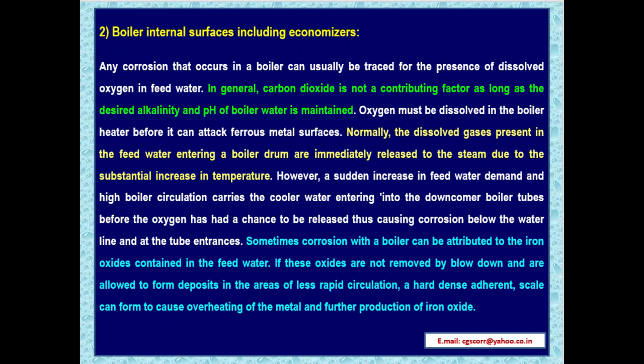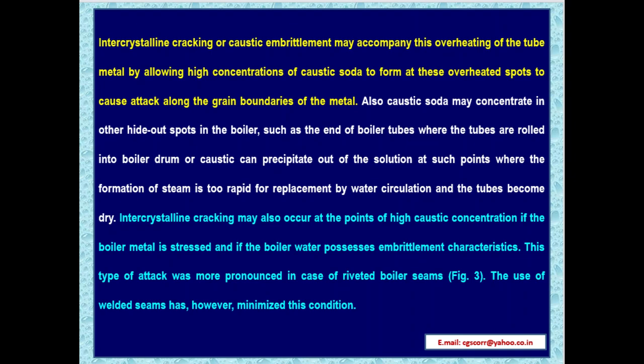Sometimes corrosion within a boiler can be attributed to the iron oxides contained in the feed water. If these oxides are not removed by blow down and are allowed to form deposits in the areas of less rapid circulation, a hard, dense, adherent scale can form to cause overheating of the metal and further production of iron oxide. Intercrystalline cracking or caustic embrittlement may accompany this overheating of the tube metal, by allowing high concentrations of caustic soda to form at these overheated spots to cause attack along the grain boundaries of the metal.